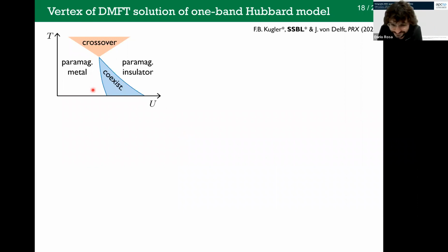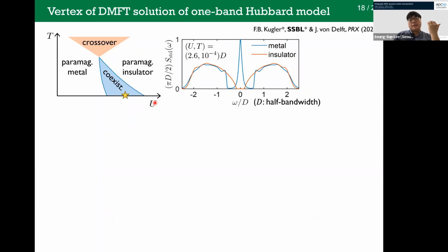Okay. Good. So for this, we have chosen the DMFT solution of the one-band Hubbard model. So this is a schematic phase diagram. When interaction U is large, the system will be insulating, and when small, metallic. In the intermediate regime, we have a coexistence regime. So it means that a system can be in both phases. So this is the local spectral function. The blue line is for the metallic solution, where we have the quasiparticle peak at the Fermi level, and the red line is for the insulating phase, where we have a gap.